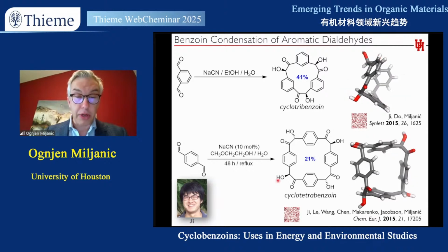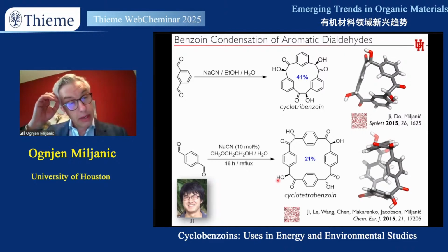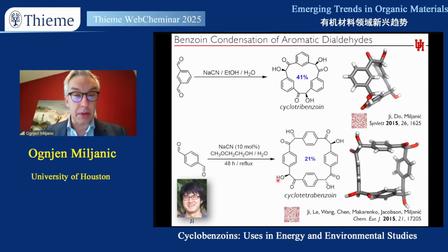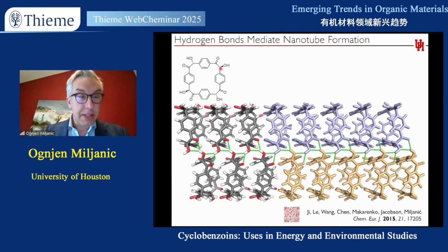Cyclotetrabenzoin inspired more work in our group since its discovery, although we're now coming back to cyclotribenzoin systems as well. And so this specific isomer of cyclotetrabenzoin is isolated because it precipitates first, right? And you can appreciate that, of course, we could have obtained various stereoisomers of this specific molecule, as well as regioisomers of the tetramers of terephthalaldehyde that are possible. And so why does this one show up as the dominant product is explained by us by its very low solubility. And the very low solubility is explained by this marvelous crystal packing, where the molecules of cyclotetrabenzoin, if you view them from the side, are organized into this nanotube, perfectly stacked on top of one another.